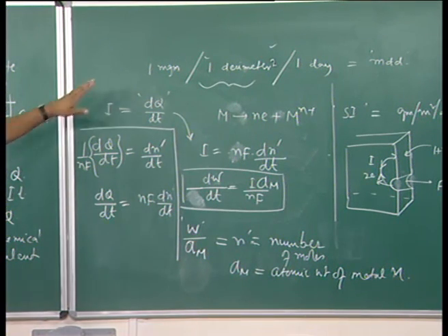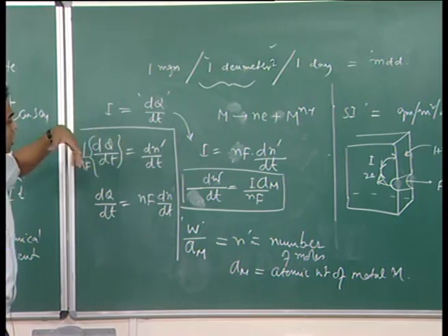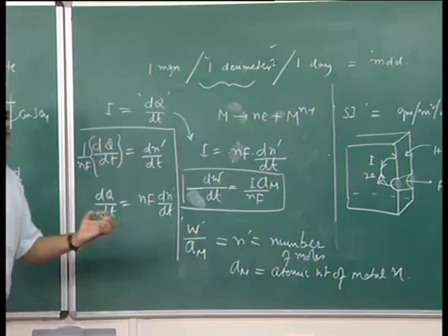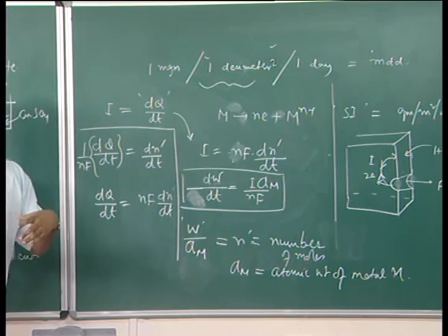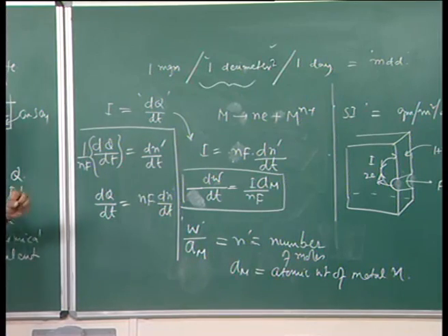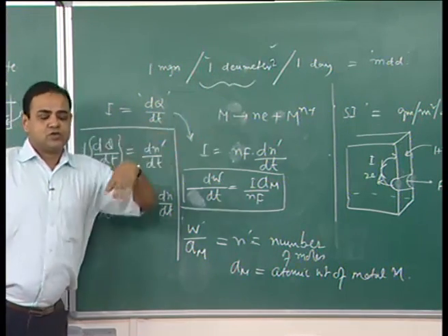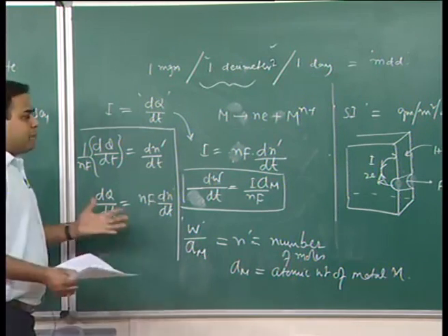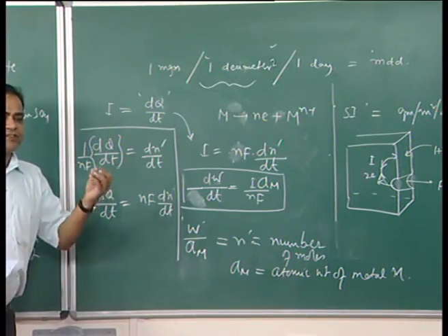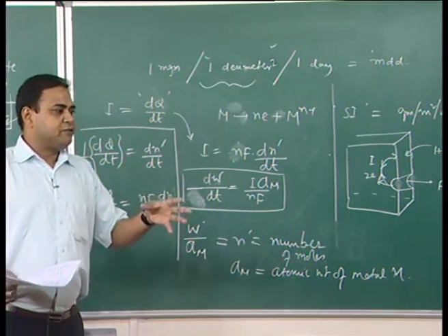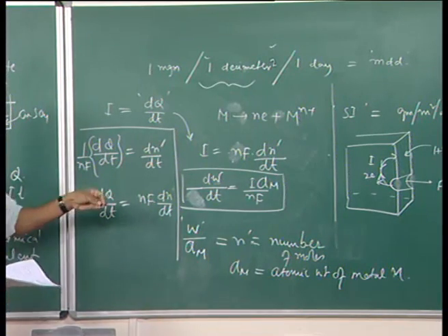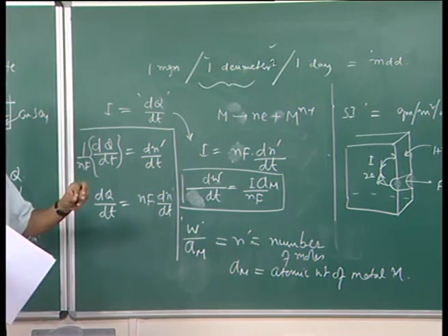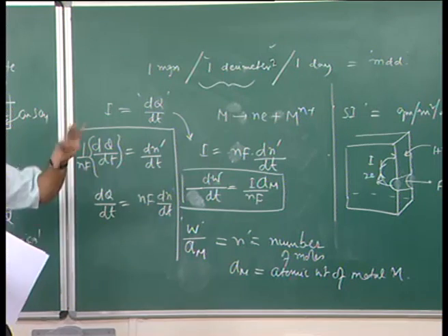Now, we have already seen that it is not good to express corrosion rate as weight loss per unit time, because the corrosion process is happening on the surface. So, it is better to divide it by the area to have a better representation of corrosion rate which can be comparable. We have seen that in the case of two pieces of iron dissolved in HCl of the same concentration, where the only change is the area, one smaller and the other bigger.